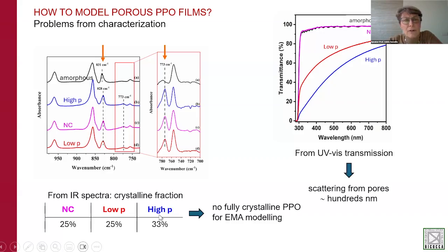Analyzing the spectra for three of our samples, of course the partially crystalline ones, we could get the crystalline fraction, and we ended up understanding that the nanocrystalline sample is not as crystalline as we thought. Well, at least myself, not being exactly deep into the subject of polymer physics. So the first basic idea, trying an effective medium model, was not perfectly applicable, in the sense that we did not have the extreme amorphous and crystalline phases, and one of the two porous. We had some mixed phases.